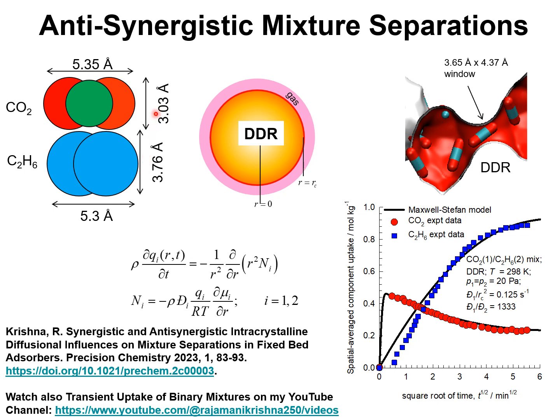strategy relies on anti-synergy between mixture adsorption and diffusion in microporous crystalline materials. In particular, I'd like to consider separations using DDR zeolite that consists of cages separated by narrow windows with an aperture size 3.65 angstrom. The shortest aperture distance and the longest distance is 4.37 angstrom.